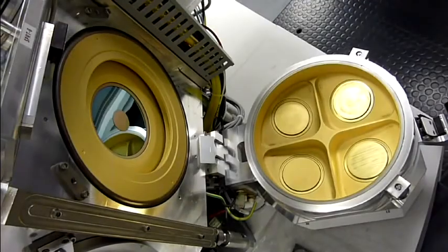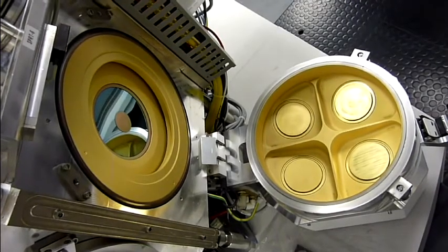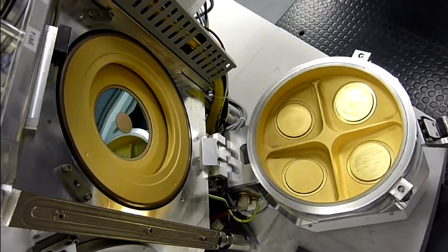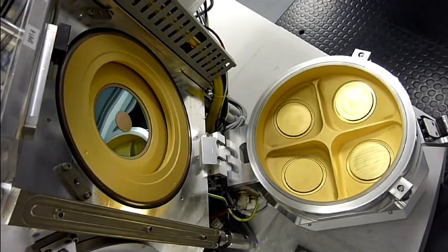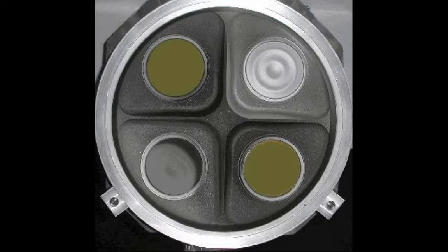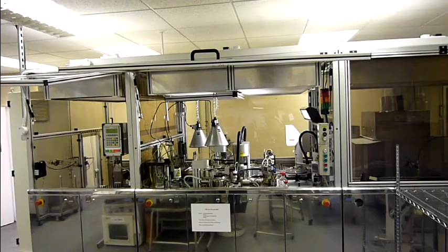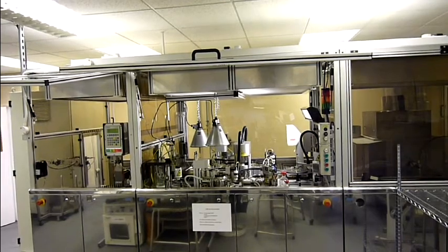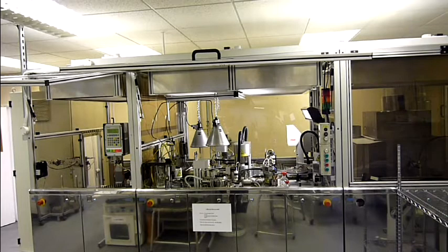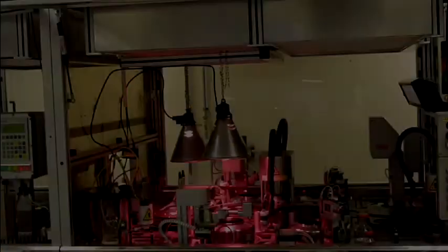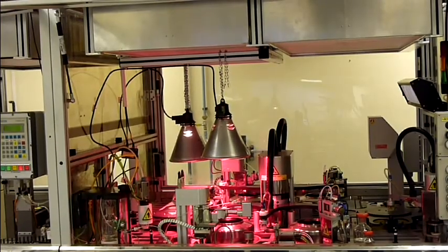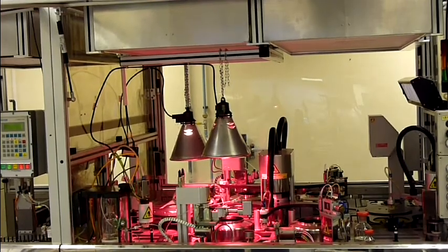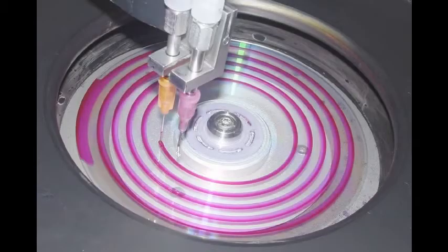One of the target positions in the coater holds an array of 4 distinct materials, which can be co-sputtered into a single layer. This allows the deposition of combination layers, or the creation of alloys in situ. For the deposition of organic thin films, a spin coating machine, originally used for CDR production, can coat thin films of organic, solvent-soluble material with a nanometer accuracy similar to that of the vacuum coater, all controlled by a versatile spin program and dispense control.